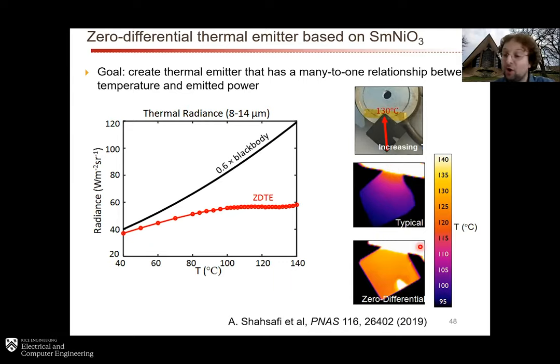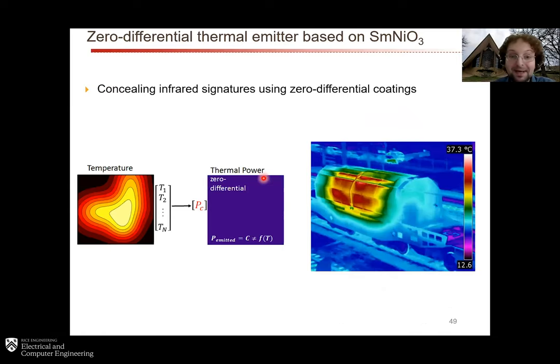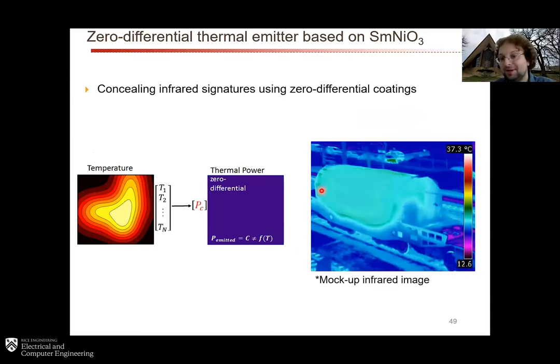And you don't see this gradient at all in the zero differential case, because even though there is a temperature gradient, there is also an inverse gradient in emissivity. And so when you multiply the Planck distribution by the emissivity, you get a constant as a function of position all the way across the sample. And so we thought this was quite exciting, because you could imagine concealing infrared signatures using this approach, taking, for example, this train car that has something hot on the inside. In this case, it's actually radioactive material on the inside, and coating it with a surface that makes the total amount of thermal radiation constant. So we think that it's a compelling, maybe camouflage is not exactly the right term, but a privacy shield type of coating.